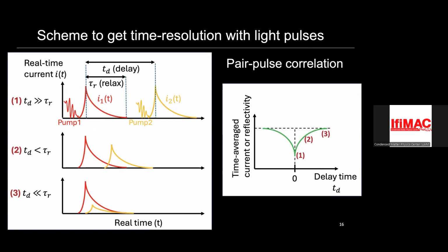So we have two consecutive pulses. So then this is the second laser pulse, and then the same thing happens. And what we do is vary the time difference between these two pulses. So when the two pulses are very far away from each other in time, then the system has independent responses. But when the two pulses start overlapping, then the response of the system is not the same because the system hasn't fully relaxed. Okay. So what we do is we measure average tunnel current.